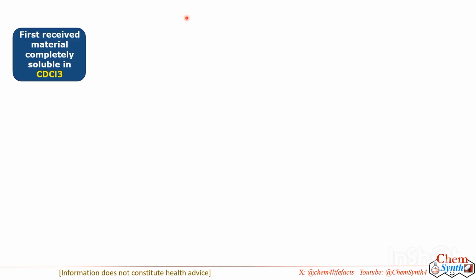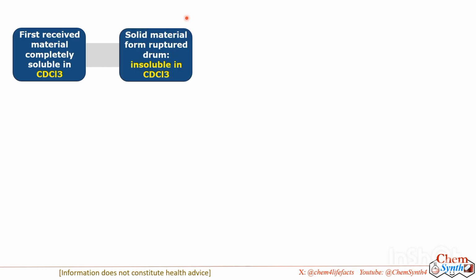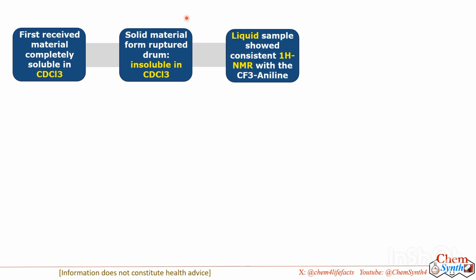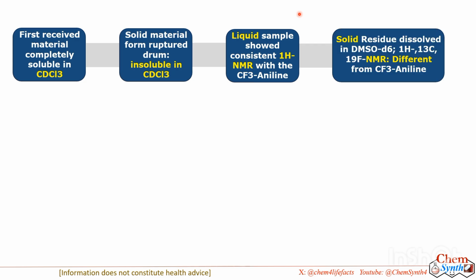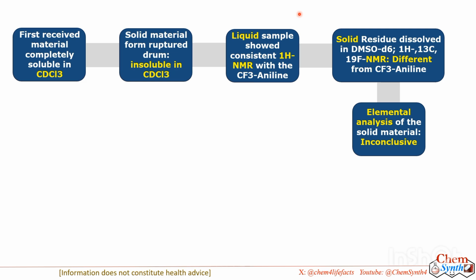First, they wanted to record NMR spectra of both the solid and liquid samples. They checked that the liquid sample was completely soluble in CDCl3, but the solid material was completely insoluble in CDCl3. For the liquid sample, they measured the proton NMR spectra, and it was identical with the actual molecule, para-Trifluoromethyl aniline. The solid material they then tried to dissolve in DMSO D6, and they found it is soluble, but the NMR spectra is different from the original molecule. They tried elemental analysis for that solid material, but it was inconclusive.